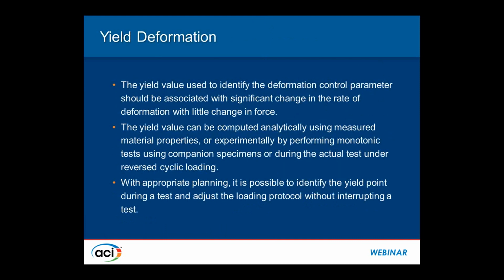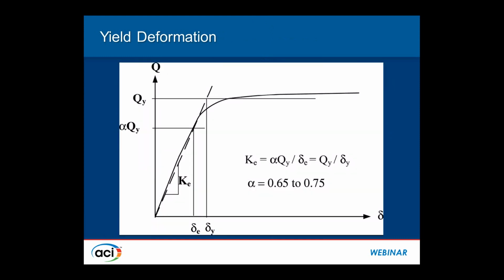This then brings up the challenge of defining yield deformation, because in a reinforced concrete section where you may have different numbers of bars at different locations, yielding may be progressive, and hence there may not be a fixed yielding. It may be gradual, and yet for columns and beams, you can pretty well identify member yielding as opposed to section yielding. And member yielding would be if the overall resistance of the member remains constant as deformations are increasing at a faster rate. That is the point to capture, and this can either be calculated prior to the test based on the material properties that we have established by standard testing, or it can be captured during the test, or there are different techniques available to help us identify yield deformation.